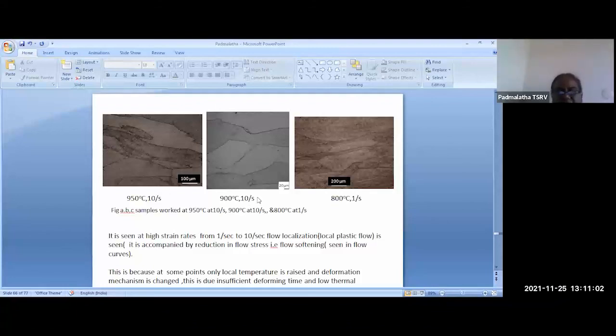So we have not given enough time. The entire process is a non-equilibrium process. So it would have happened that at some regions only the material would have been heated up. Some adiabatic heating would have taken place at certain points. And for titanium the thermal conductivity is also low. Because we didn't give enough time for the heat to distribute throughout, only in some areas the localized heating would have happened, and only in those localized areas the deformation behavior is changing. Such a condition we call flow localization. It means the flow is localized in some areas.